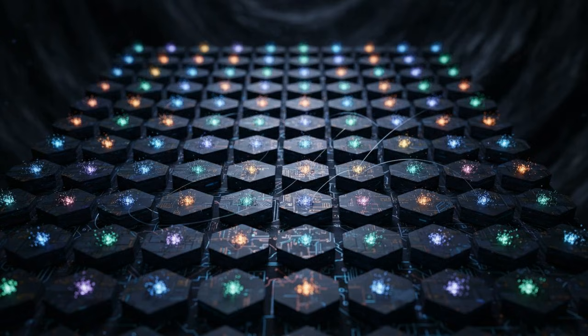And the field has expanded beyond carbon. The principles of Twistronics apply to any 2D material held together by van der Waals forces. For example, transition metal dichalcogenides, or TMDs, are semiconductors. When you twist bilayers of these materials, you get moire excitons. An exciton is a pairing of an electron and an electron hole. In twisted TMDs, the moire potential traps these excitons in specific spots, creating arrays of single photon emitters. Imagine a grid where each cell can trap and release exactly one photon at a time. This is a holy grail for quantum information technology.